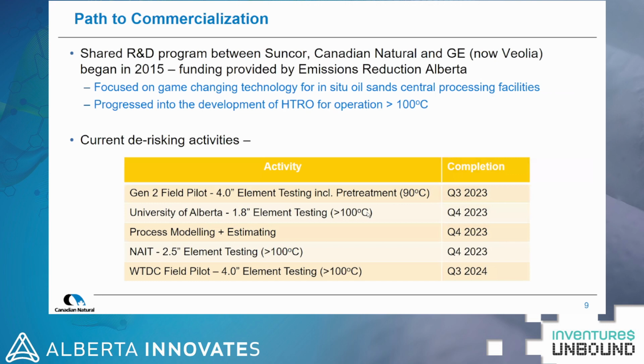So some of our current activities, we have a Gen 2 field pilot. That's 4-inch element testing, including the pretreatment at 90 C. That's actually a different program. It's merged to a certain extent with this new initiative. It's targeting 90 C. The new initiative is targeting above 100 C.